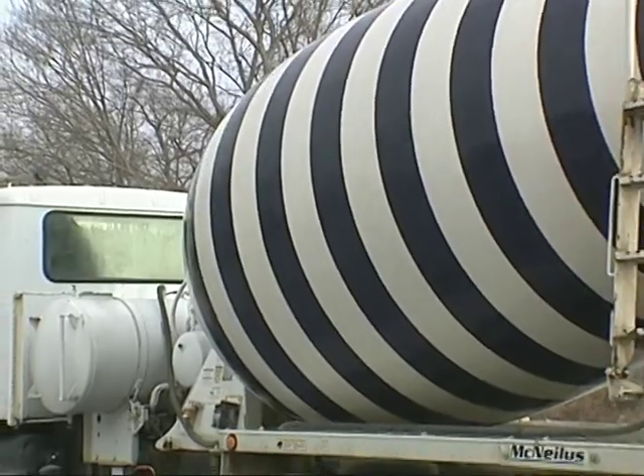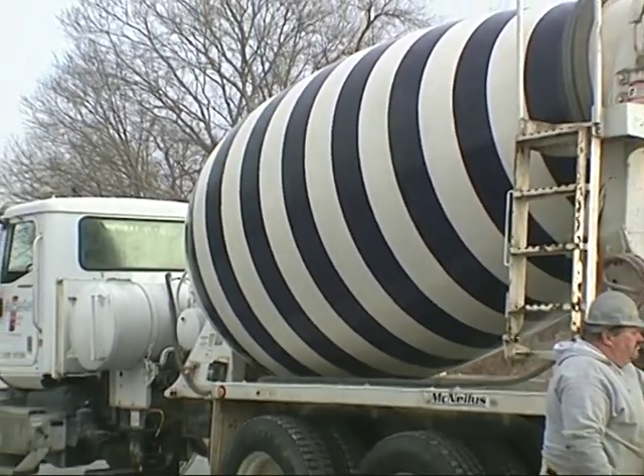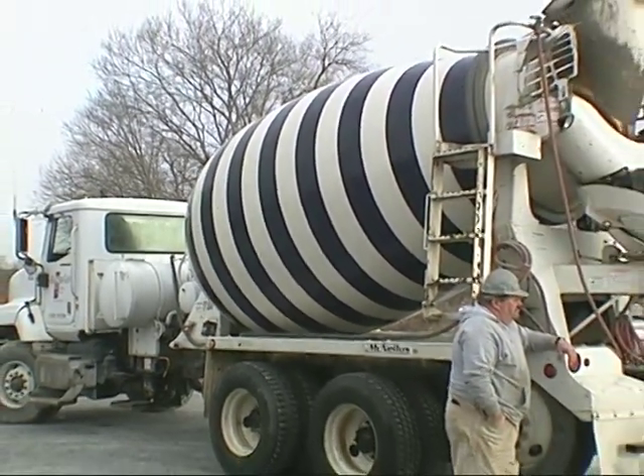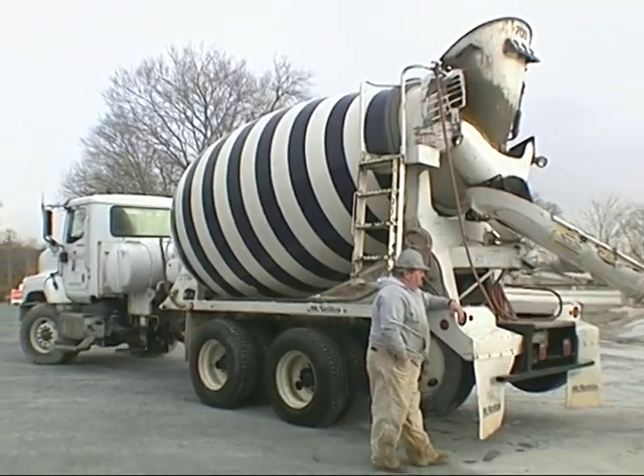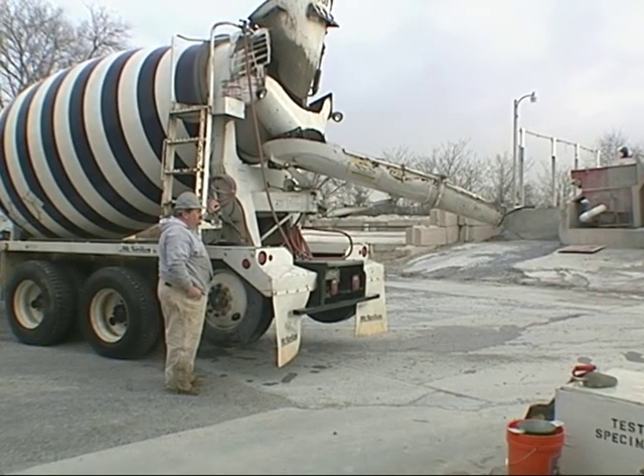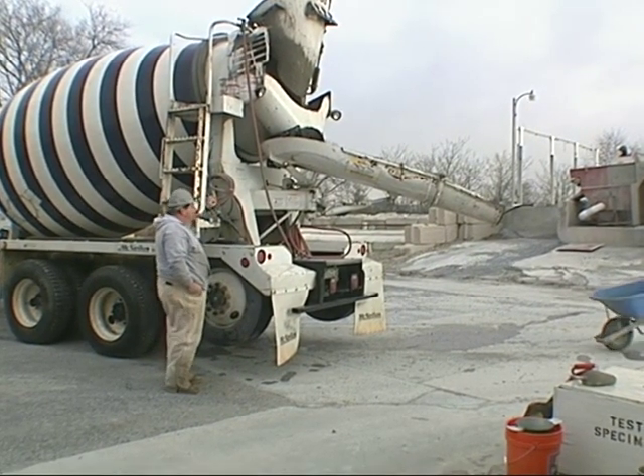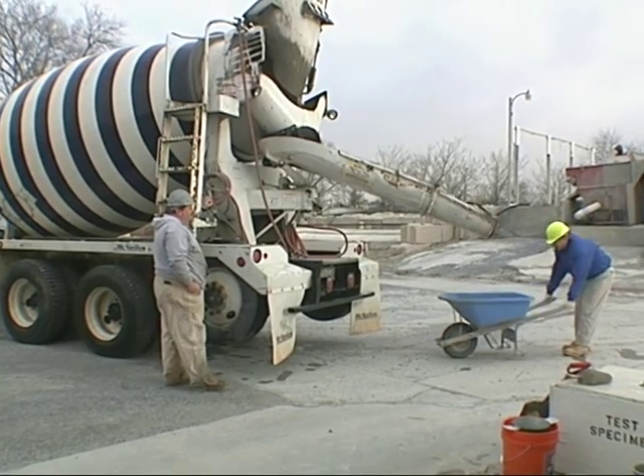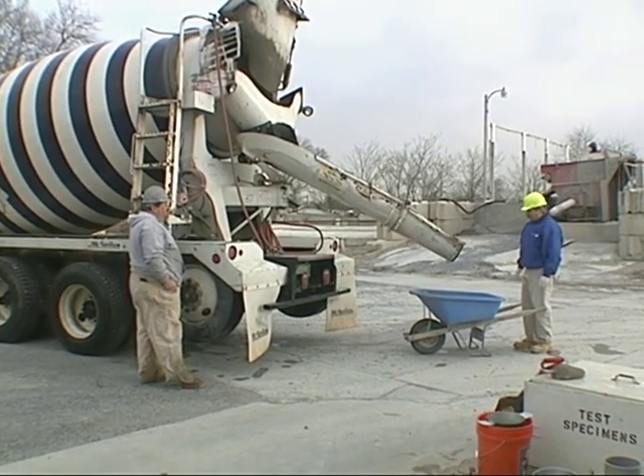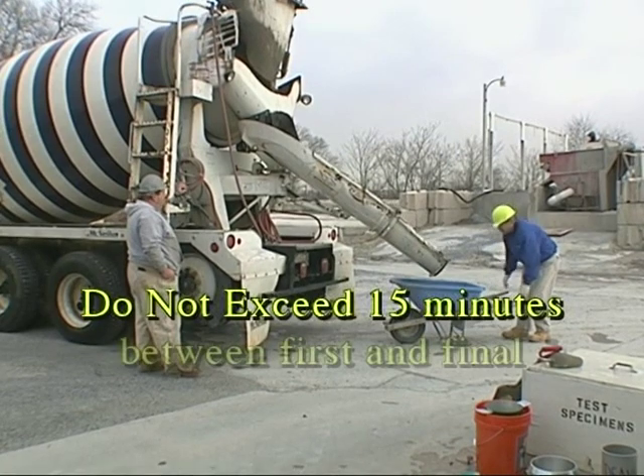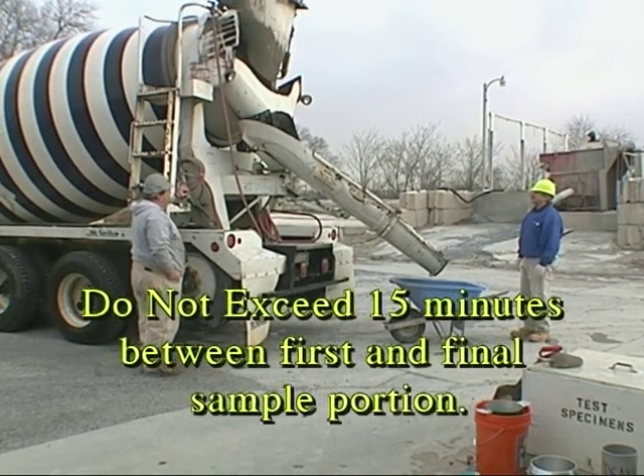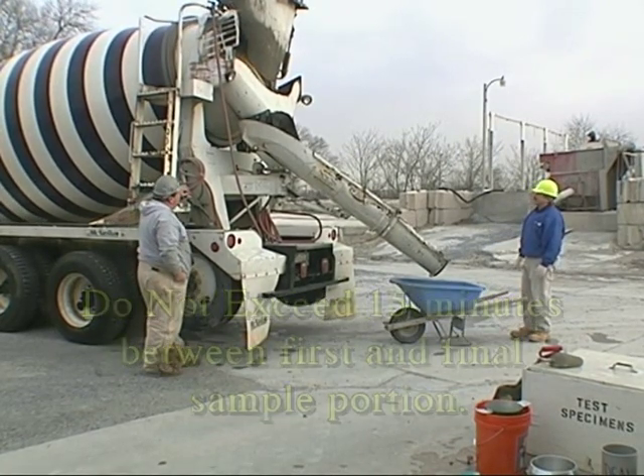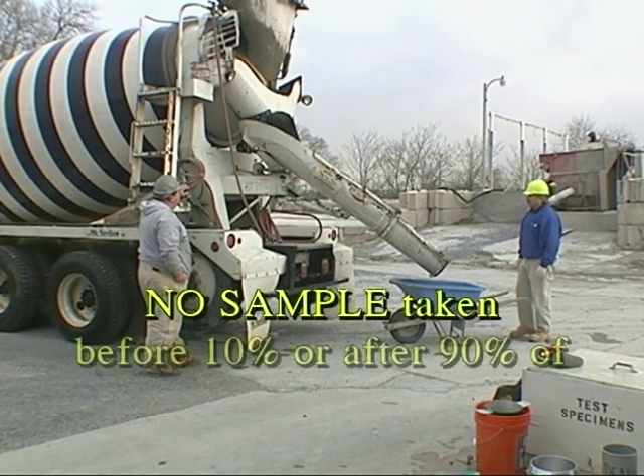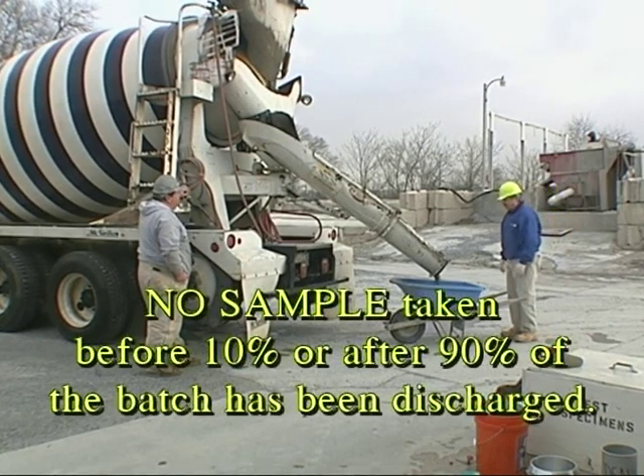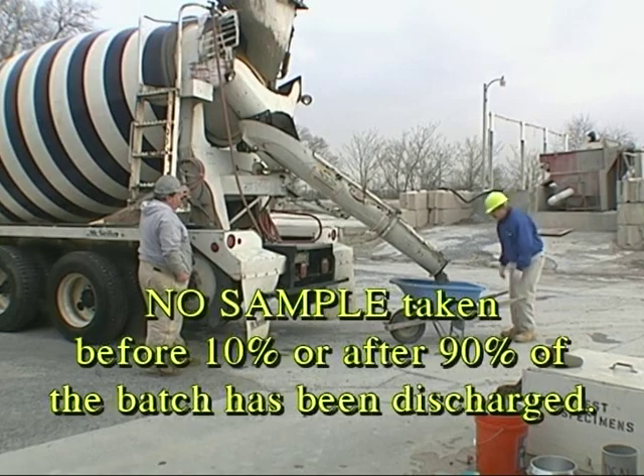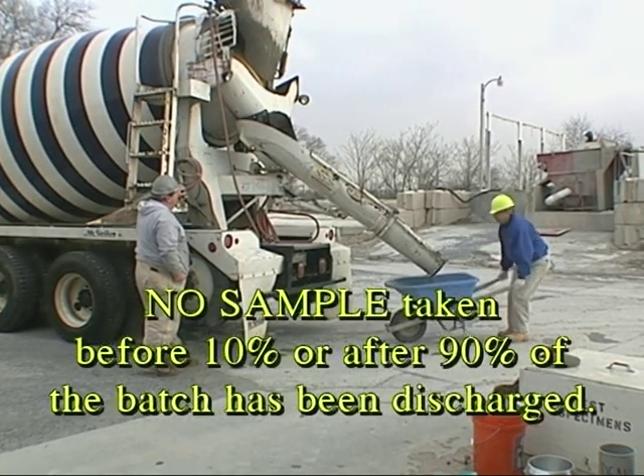1. Make sure all the water is added to the mixer before sampling from the truck. 2. Sample the truck in 2 or more regularly spaced intervals from the middle of the batch, not to exceed 15 minutes between the first and final portion. In all cases, no sample should be taken before 10% or after 90% of the batch has been discharged.